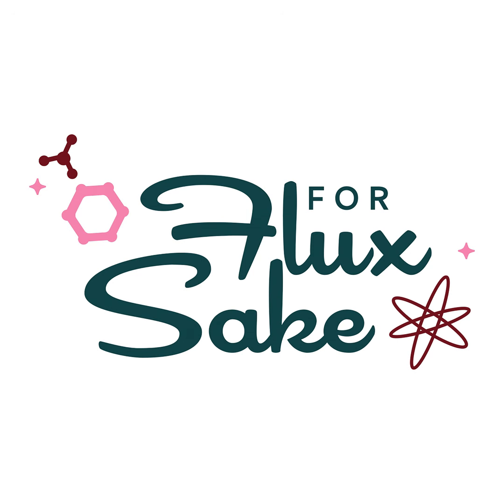And that layering doesn't do that. And I'm having a really hard time thinking of any of my professional friends who are really actively using layering as a professional. The one I can think of is Stephen Hill, but it's because he's doing a very specific crystalline thing where, for one, he's once-firing. He's also spraying the glazes on, controlling different glazes, but it's not layers as much. With his, it's spray, so there might be more overspray, but he is putting specific glazes on specific geometry for a specific effect. It's not layering per se.